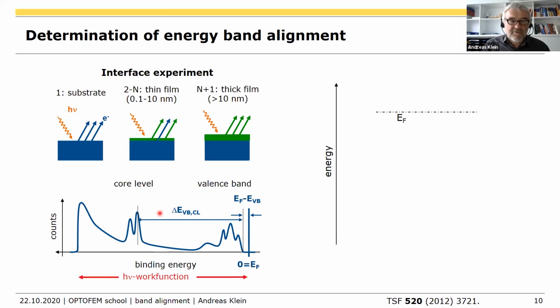Okay, so now how do we get the barrier height? This is the energy diagram. Here is our Fermi energy. We start with a clean substrate, so we know the Fermi level with respect to the valence band maximum. It's this quantity. And we know the distance between the valence band maximum and the core level.